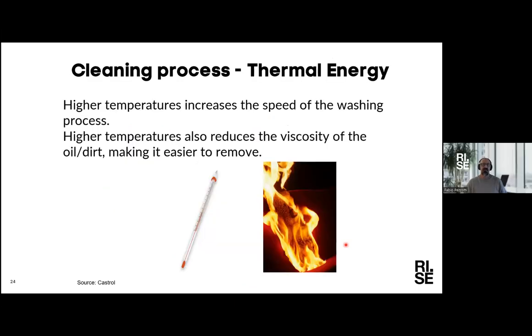Regarding the thermal energy, as I said, it's very related to the temperature at which the cleaning process is being held. At higher temperatures, it increases the speed of the washing process. It can also reduce the viscosity of some of the contaminants, in this case oil, dirt, and it can make it easier to remove. One of the drawbacks with the thermal energy is, of course, that higher temperatures mean that you will need to give more energy to the system. And this could be not the best energy efficient, as you can say. But as I said before, it's all a balance between the different stages in the cleaning process.